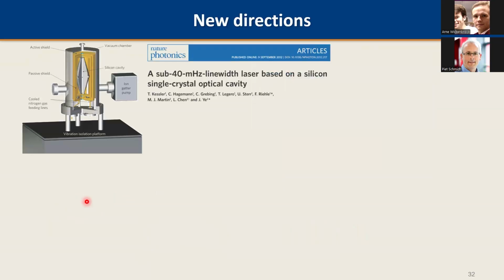I don't have the time to go into much detail on this, but one way to mitigate that thermal noise is interesting. The fact that thermal noise was actually limiting all cavities up to then was only discovered in 2004. That's 21 years ago. Up until then, people thought they just needed to get higher finesse mirrors, improve their electronics, and just get better. But nobody did, despite trying really hard. And then they discovered a thermal noise issue, that this was the actual limitation. It was dead on the best cavities that were available at the time.